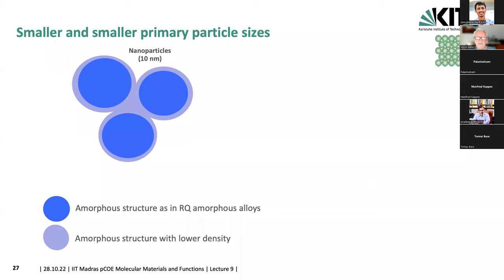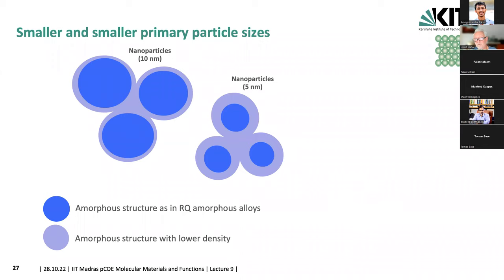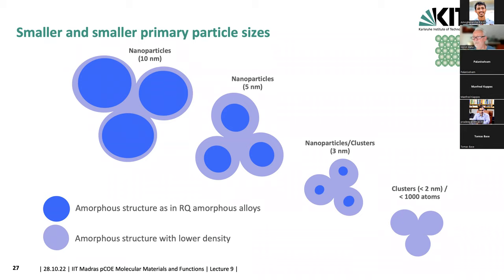So the idea was, if we go to smaller particles, let's say to 5 nanometer, the fraction of this interfacial region should go up. And if you go smaller, it should further go up. And if the structure of this light blue amorphous phase is stable in itself, maybe it would be possible to make something like this, where this darker blue rapidly quenched structure would not even be there anymore. And I think this would be a beautiful result, because it would show that we have missed over decades that the amorphous structure has much more variation than was ever anticipated.